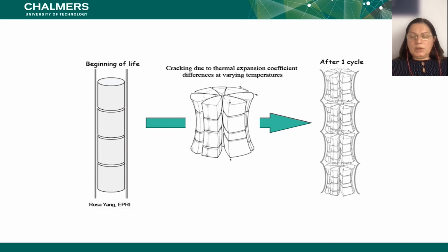So basically what we were talking about until now is this: in the beginning of life, we have a beautiful stack of pellets. Everything is in order. Then you have the fuel a longer time in the reactor, and depending on the type of the fuel, of course, not all fuel is swelling that much, but let's say oxide fuels are swelling quite a lot. And then after one cycle, this is of course an extreme case you see here, but after one cycle you can get a lot of swelling and a lot of deformation of the initial nuclear fuel.